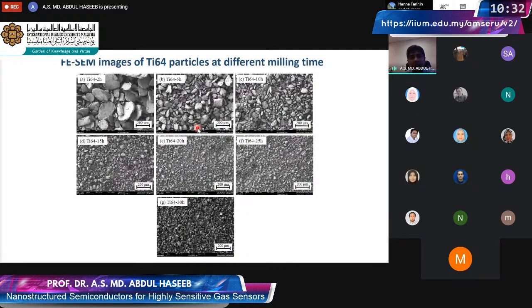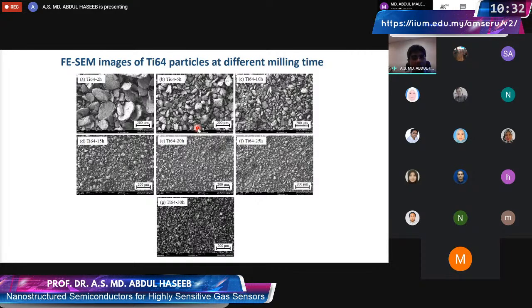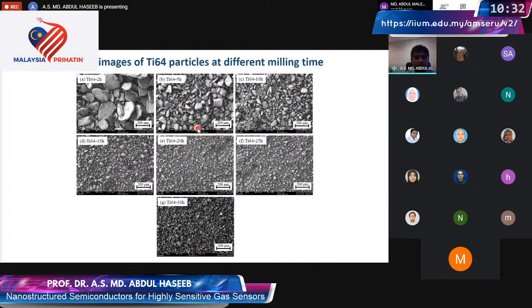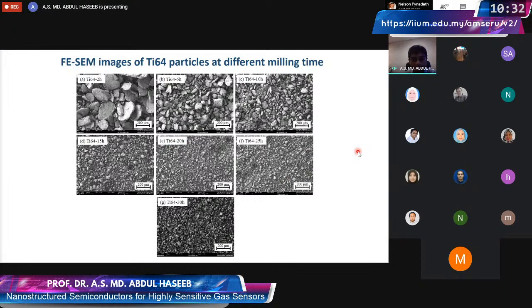Then we wanted to see the effect of residual stress, and we imposed the residual stress by ball milling. So we subjected the incoming material, the Ti64 particles that we saw, to ball milling for different time periods. If the time is longer, then we induce more stress.